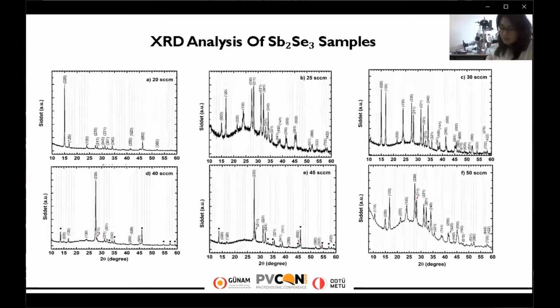Now we see the 6 graphs of XRD analysis results. First, I want to talk a little bit about the crystalline structure of this compound, antimony selenide. The binary compound antimony selenide has an orthorhombic crystal structure, which belongs to the space group PNMA 62. To improve the performance of the solar cells, the control of the crystal orientation of the antimony selenide film is a key factor. But it's valid for all other semiconductor materials used in solar cell technology.